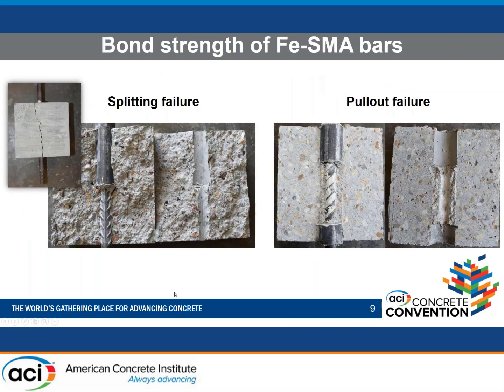So before showing the results, I'm presenting here the mode of failure for both splitting failure and the pull-out failure. This was the splitting, cracked. It's very clear as we see. And when we open the specimen, it was already damaged. So you can see the splitting failure. And it's clear if you look here, the rib marks are still on the concrete. So there was no pull-out at all. It was pure splitting failure. And again, this is the debonded region, and this is the bonding region.